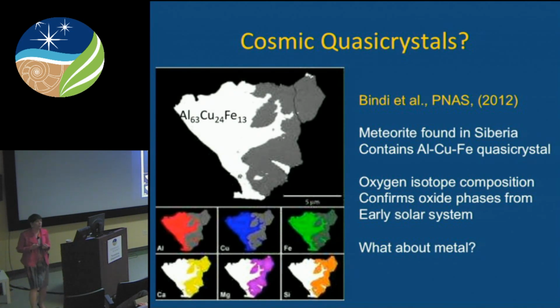And one of those is illustrated by the so-called meteoritic quasi-crystals. I first became well acquainted with this material in a seminar given here by Paul Steinhardt, and I was so excited for this to be reality because my PhD thesis is on metallic quasi-crystals, not the aluminum systems, but the titanium systems. And my current research involves a very heavy component that's meteoritic. So I thought this was really just made for me. But it's too good to be true.